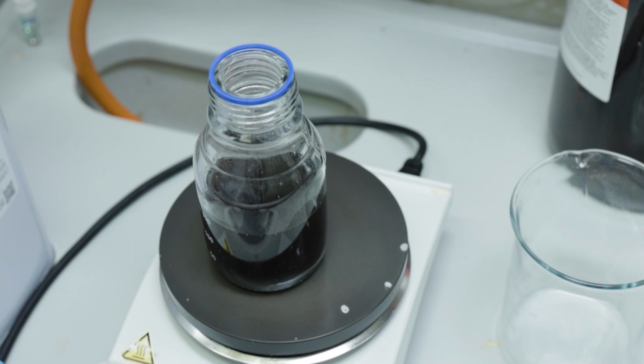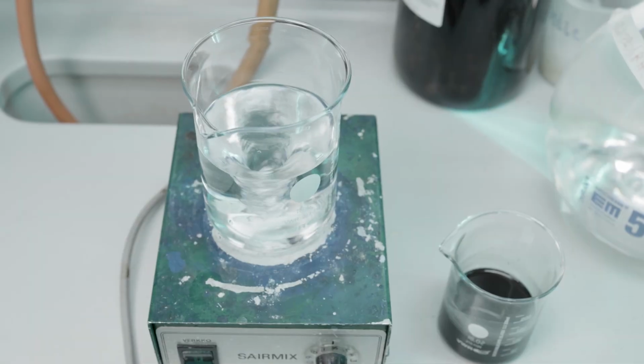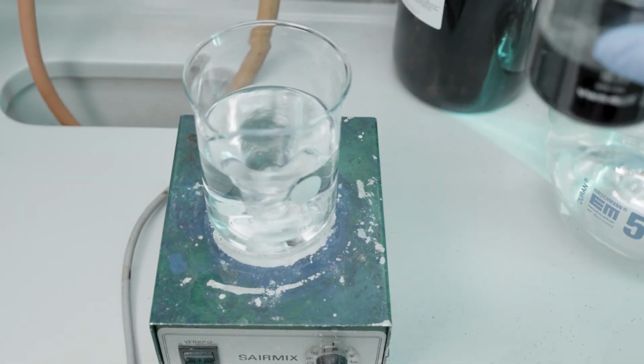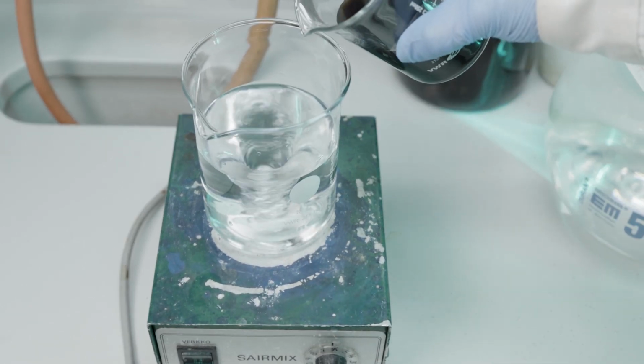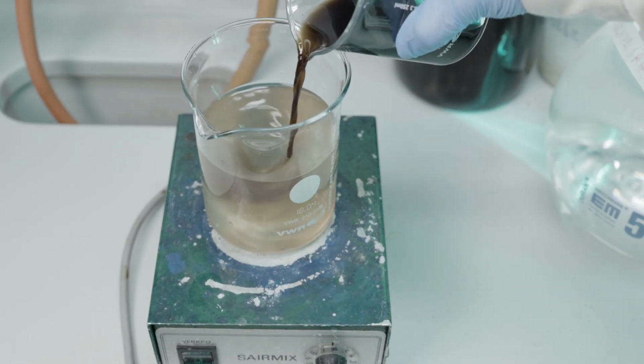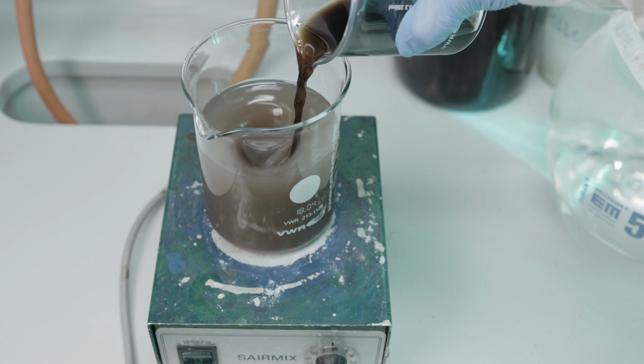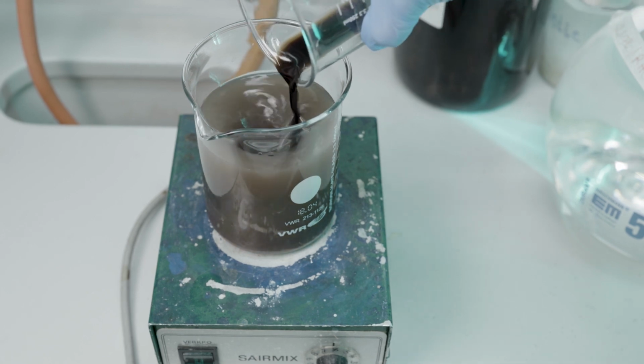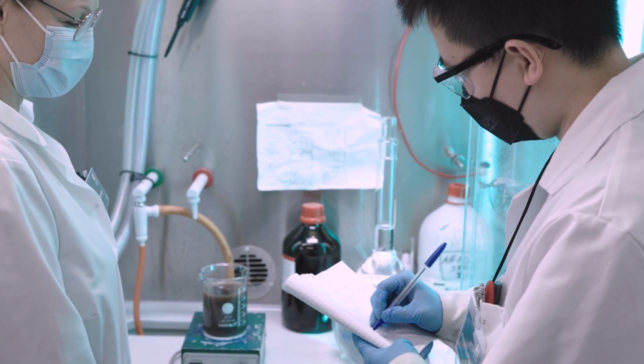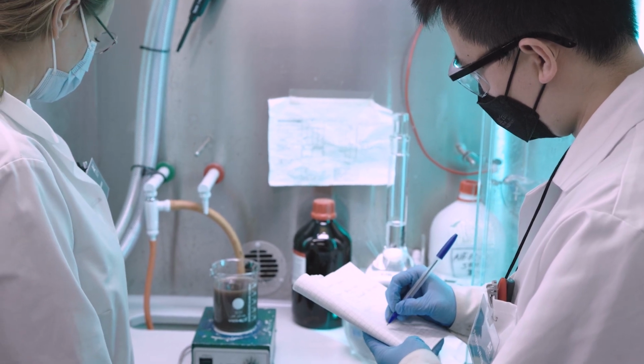The lignin solution is then added into water, acting as an antisolvent, and on contact with water, lignin spontaneously assembles into spherical nanoparticles. The largest and most hydrophobic lignin molecules form the core of the particles, and the smaller and more hydrophilic molecules are enriched at the surface.